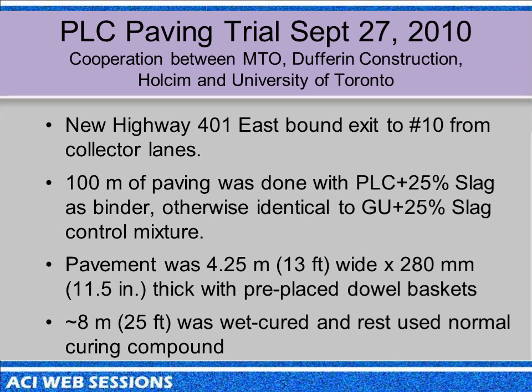Just a month ago, we did paving on one of the major highways, expressways across the top of Toronto, where they're widening the pavement. We did 100 meters of paving with limestone cement, again with slag as a binder. And we did a control section on the same lane further down so we could monitor it for scaling resistance and abrasion resistance over the next year or two. It was a 13-foot wide slip-form paving, about 11.5 inches thick, pre-placed dowel baskets. We did some playing around with curing as well. They normally use curing compound. We wanted to look at the moist curing as well.